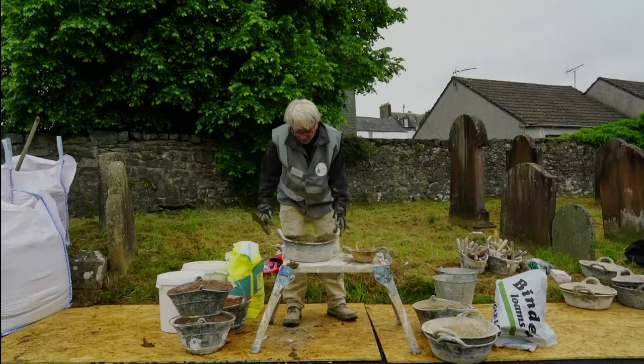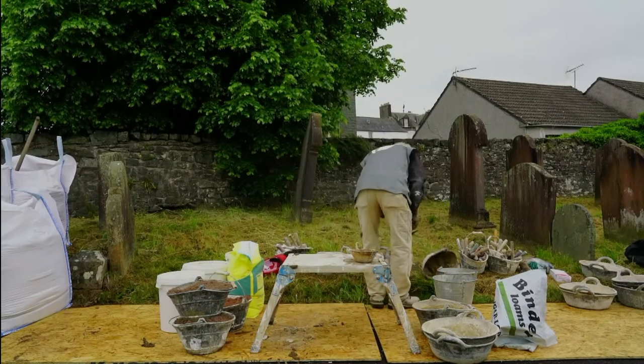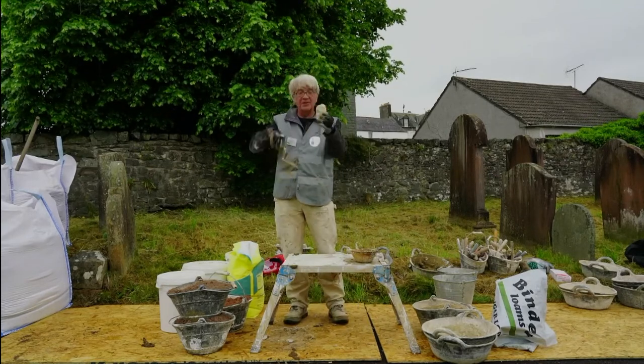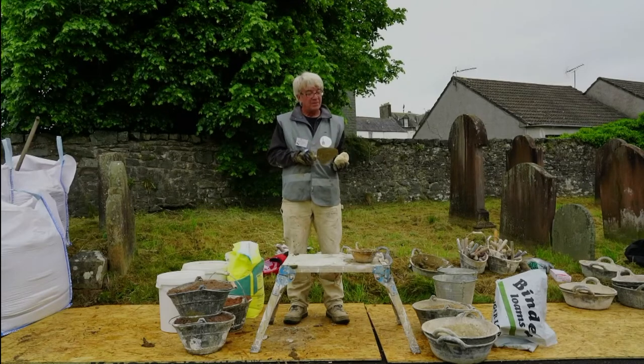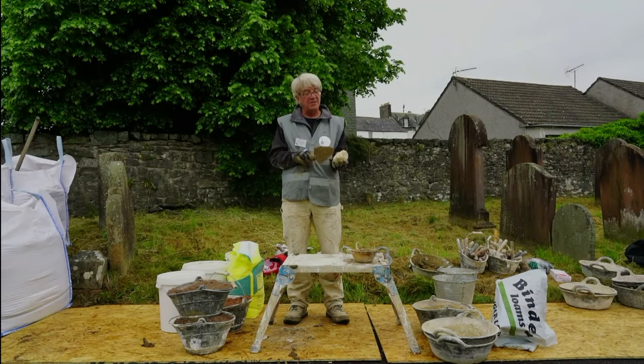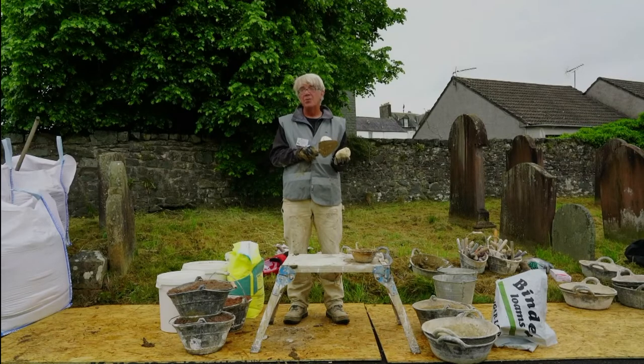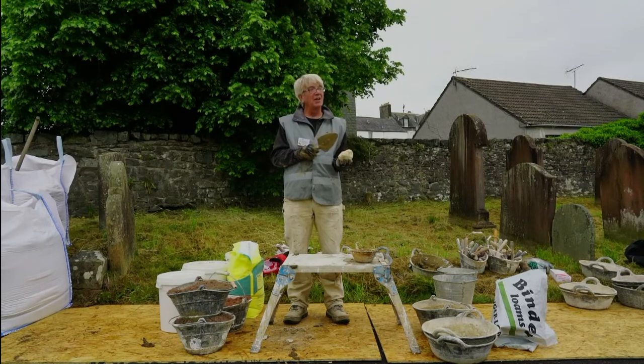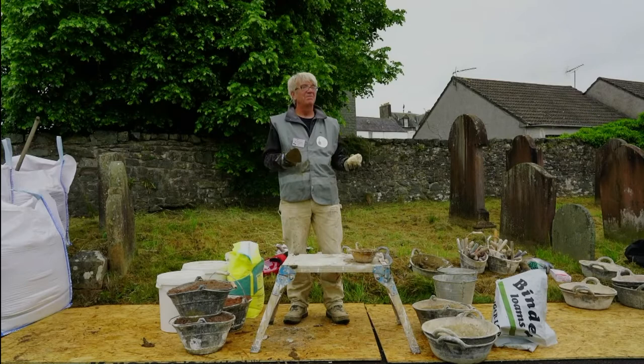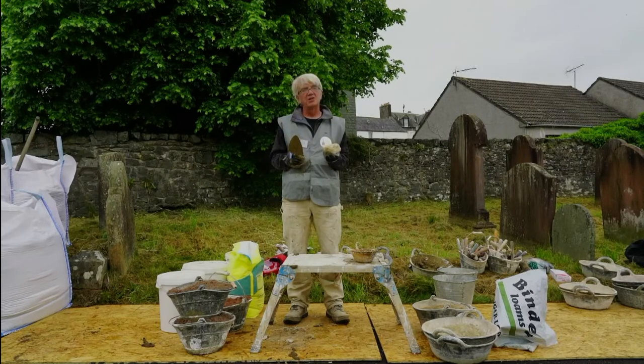I'd say to you, if you come across mortars that you think are earth, look closely. That one you don't have to look that closely. Loads of lime in there, loads of lime lumps, but earth too, and this one uniquely in my current experience. Phil Reavy, the analyst, was certain, this is from my village, that most of the aggregate in this is sand from the beck, so very, very fine. And then he's adamant that they deliberately, consciously, added 9% clay to the mortar. A real no-no, that, isn't it? You don't want clay anymore. You don't want mud in your mortar. But they added the clay into that mortar. This is 18th century from a kitchen garden wall, high status.